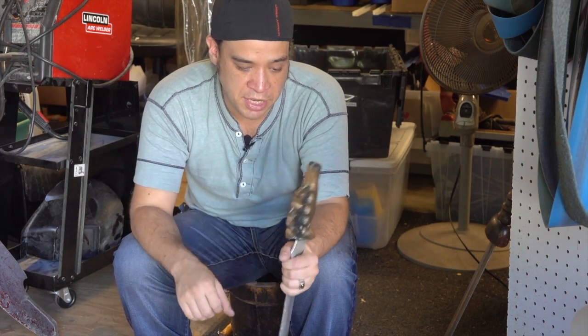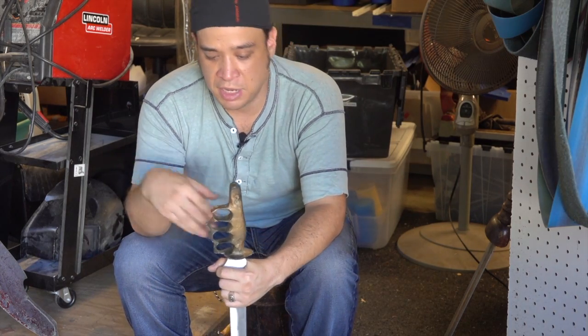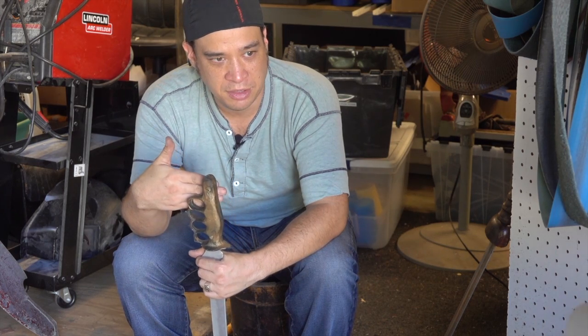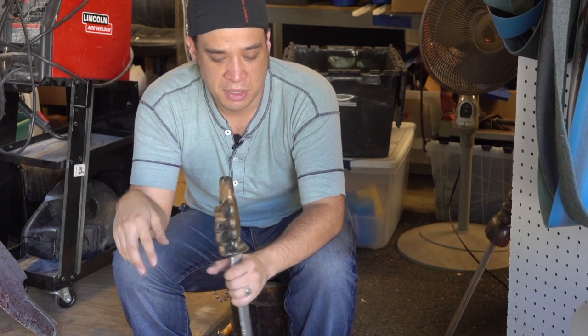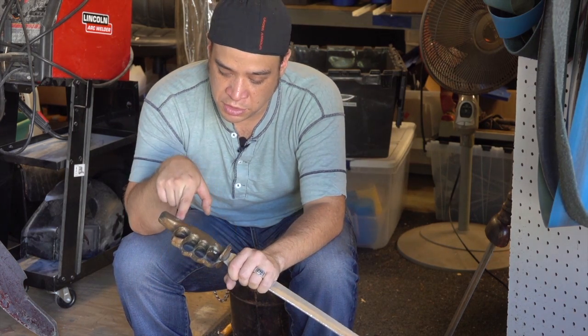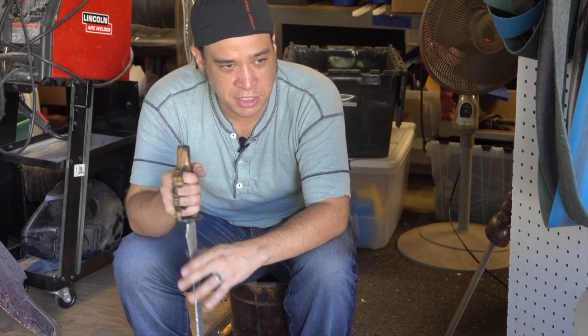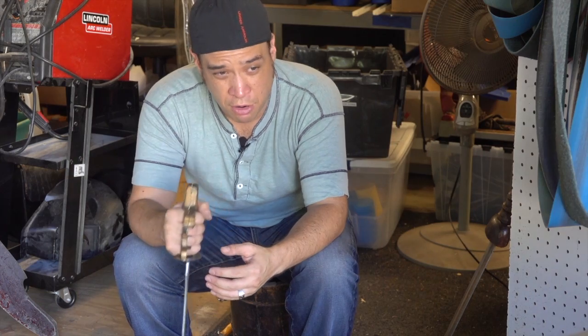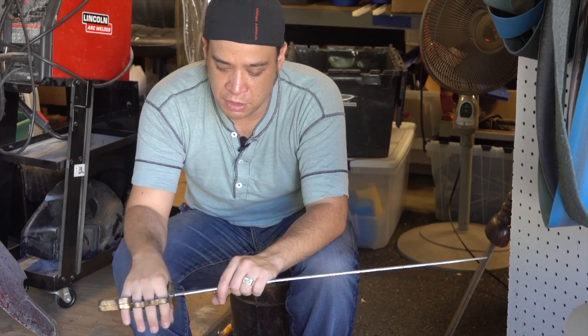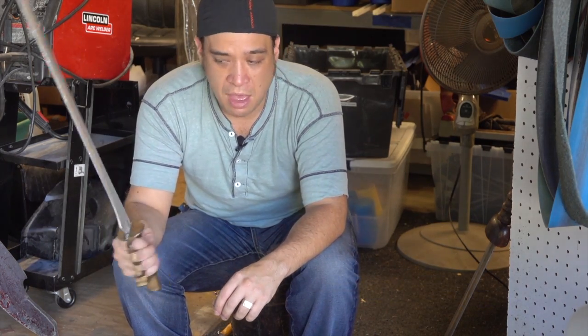And so I clamped the blade into the mold, tightened it up, and then poured it. I even had one side be plexiglass so that I could see it climbing up and when to stop. And then our pour spouts, you can see there are our vent holes. Yep, and we just snipped them off. But the problem with Onyx is that it's brittle. It's very hard, but it's brittle, and they broke on set. So they sent these back maybe during third season. So they lasted a good amount of time.